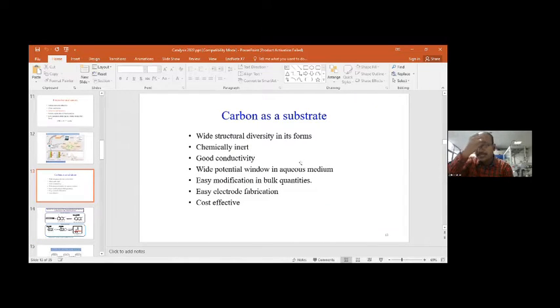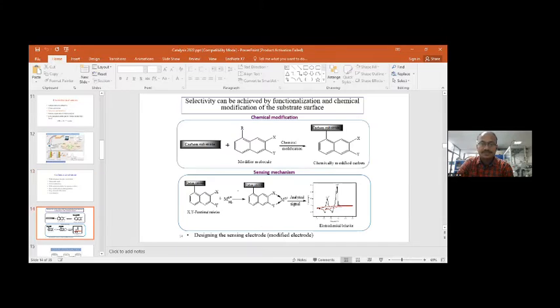Similarly, as I told you, carbon can be used as a substrate material because of the wide structural diversity in its forms, chemical inertness, good conductivity, wide potential window, easy modification, easy electrode fabrication, and cost effectiveness. That is why carbon is used as a substrate material for electrode fabrication. Selectivity can be achieved by functionalization and chemical modification of the substrate surface. On the carbon substrate we use a modifier molecule, whose functional groups are responsible for targeting the analyte. Adsorption and desorption can be easily done with these modifier molecules, and how much is adsorbed and dissolved can be monitored and recorded using the electrochemical workstation, giving us the electrochemical response.